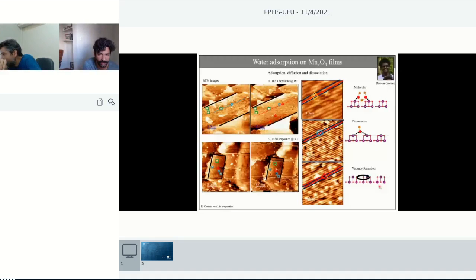So you're seeing here again an STM image, one of those STM images that you saw before, but now we are adsorbing water on top. So again, STM is based on the tunneling process, and then you are actually collecting more or fewer electrons in certain positions of the surface. But because we know that the atoms are surrounded by a large density of electrons, what you see in the STM is actually the amount of electrons that you have in a certain position. And because it's usually localized in certain positions close to the atom core, then you can say, oh, that's my atom there, right? So you're not seeing the atom, but you're seeing the electron cloud. But then usually you can directly address more electrons where the position of the atom is.